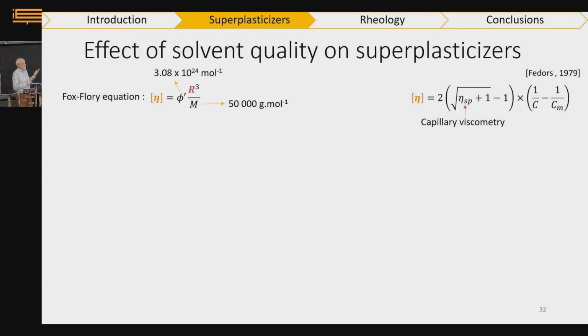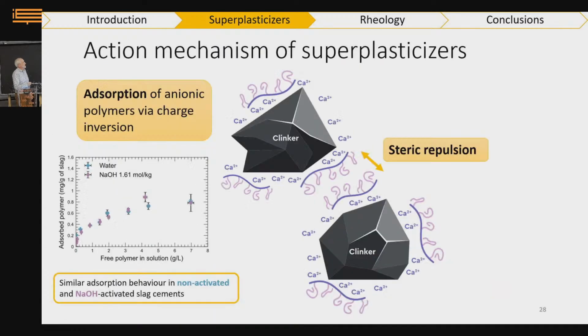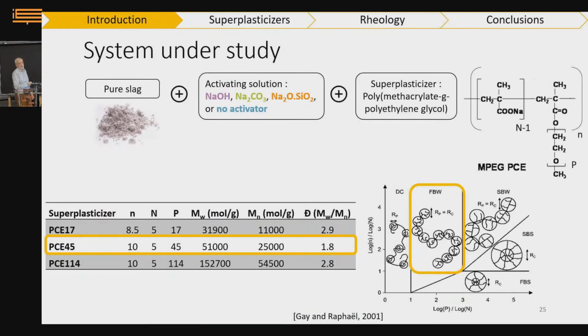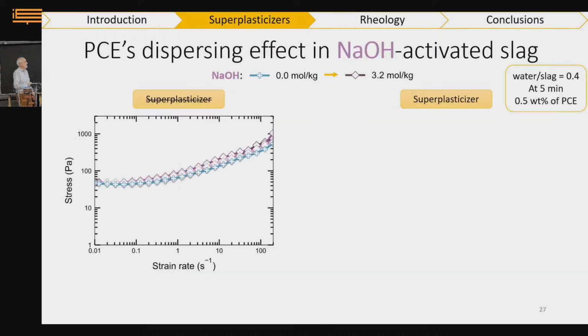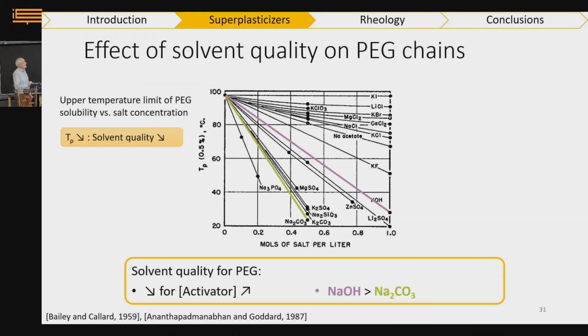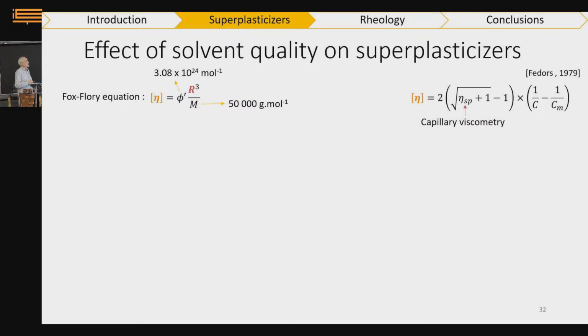So here I took a typical value, which is the one we used. And this is just orders of magnitude. If you remember, I gave you a mass that was slightly different, but it doesn't matter. We are dealing here again with scalings. Here is a parameter that describes how the monomers are distributed within the blob. And if it's Gaussian, this can be calculated. If you assume a Gaussian distribution within the blob, this gives you this value here. Some people say 3, some people say 3.5, but again, it doesn't really matter for the sake of demonstration here.